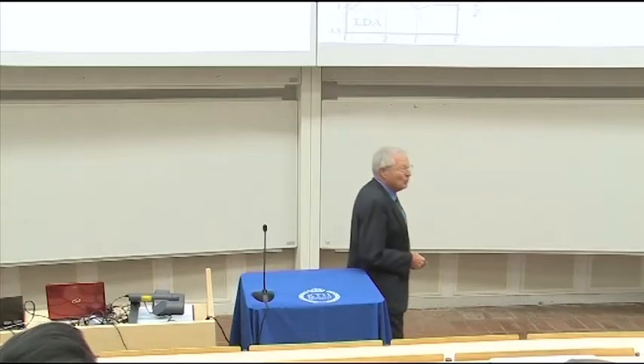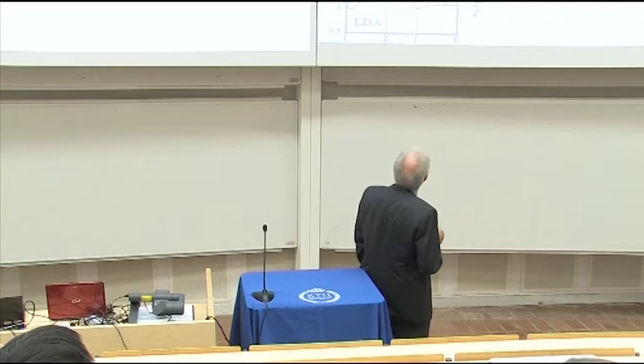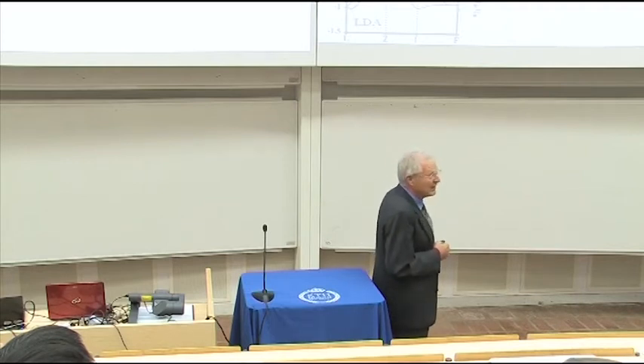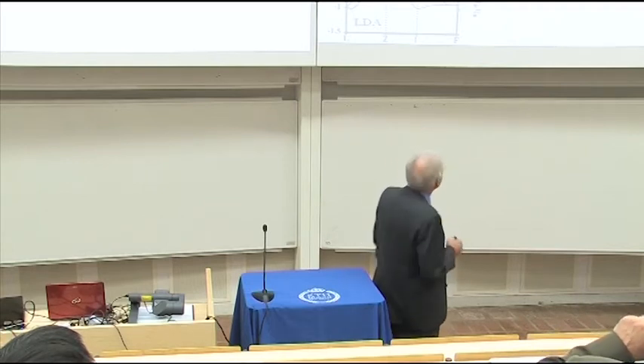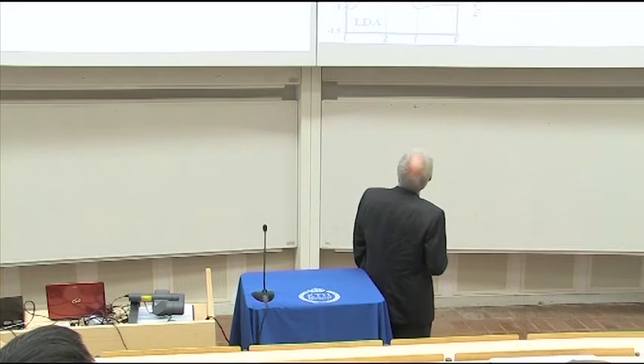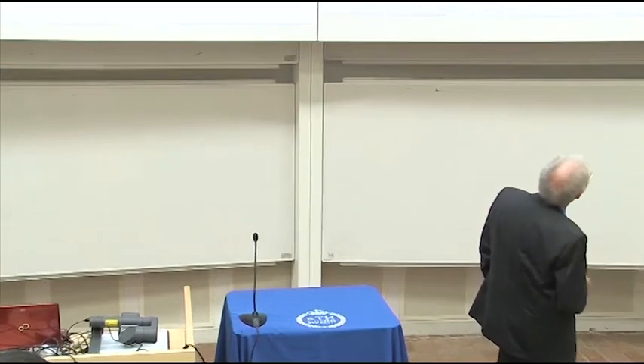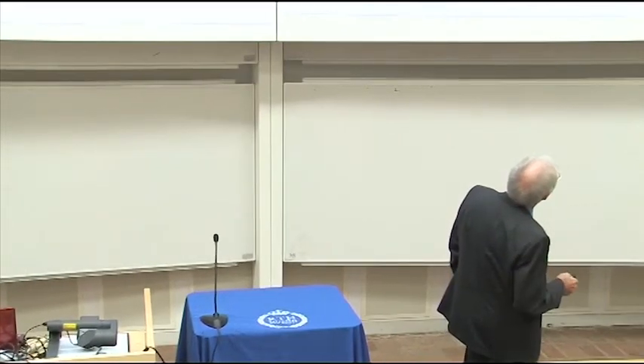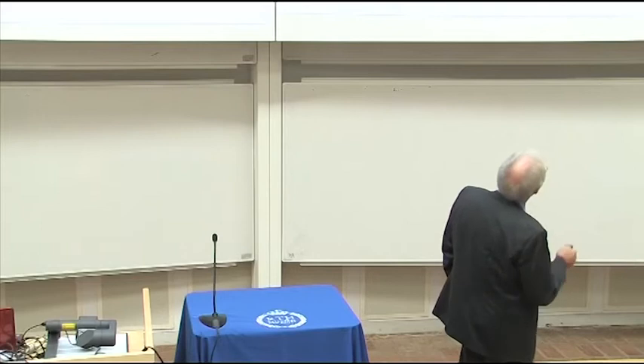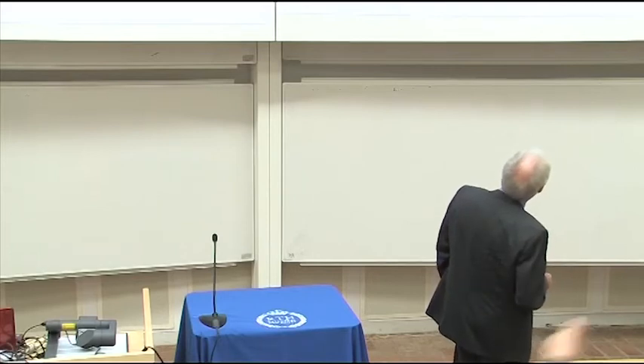Now, we did have the U, and what the U is doing, the biggest effect is of course going to singly occupy those bands. You're going to have an upper Hubbard band, which is not full, so you could try to move this Fermi level up to about here, and that would be what a spin-polarized calculation would basically give you, but that's not quite what happens. So we do DMFT - I'm not going into that - it's just adding the unscreened Coulomb terms and solving this DMFT like an Anderson impurity problem.